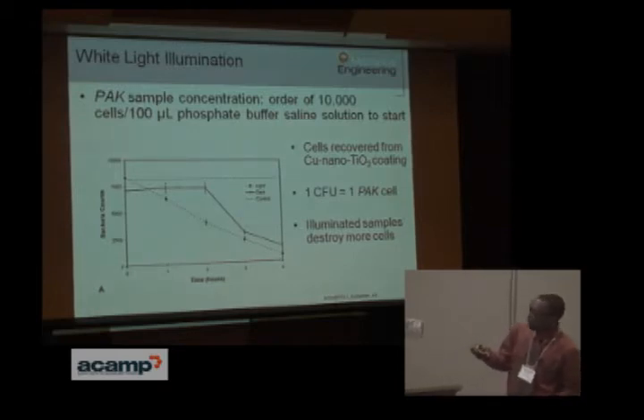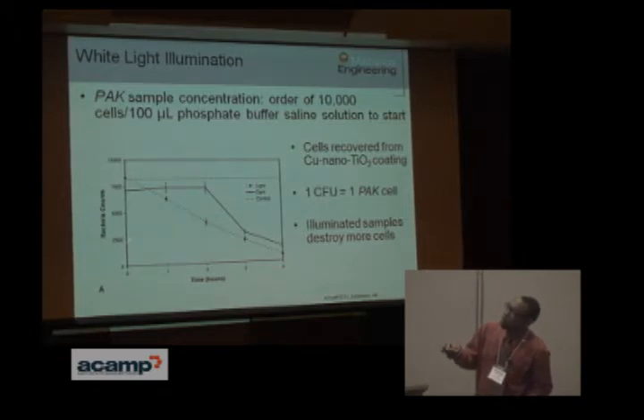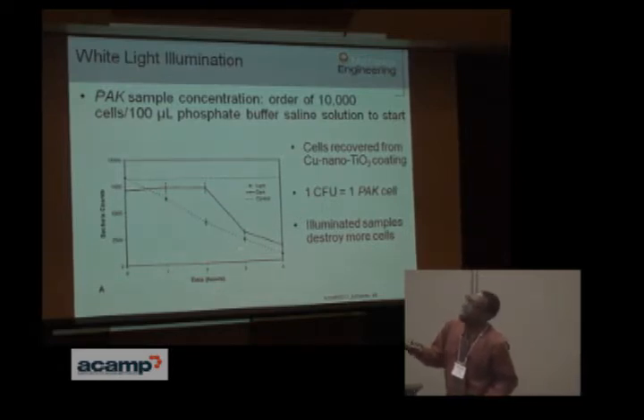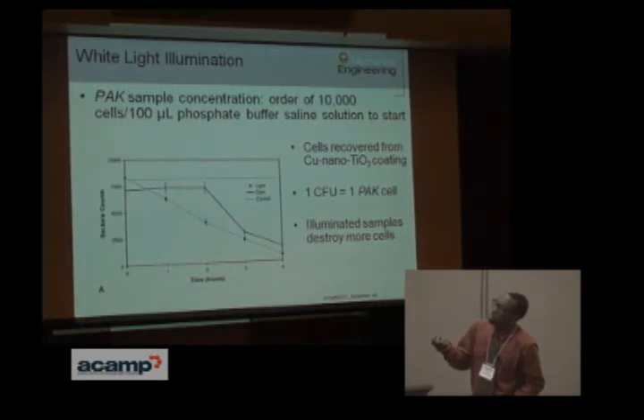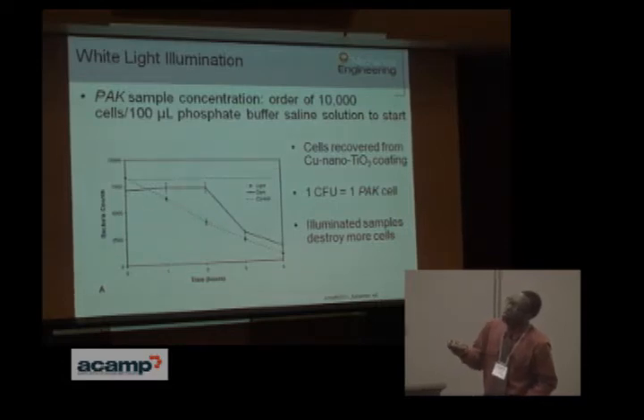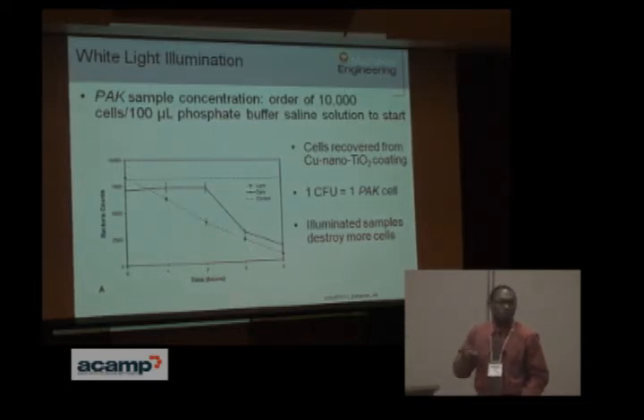surfaces. And if you look at my chart here, you'll see that I have a curve of the amount of bacterial cells in colony-forming units, where 1 colony-forming unit is equivalent to approximately 1 bacterial cell. And this is the time in hours on the x-axis here. The broken line on this curve represents the results as a result of white light illumination. The solid line represents our surfaces that were held in a dark chamber.